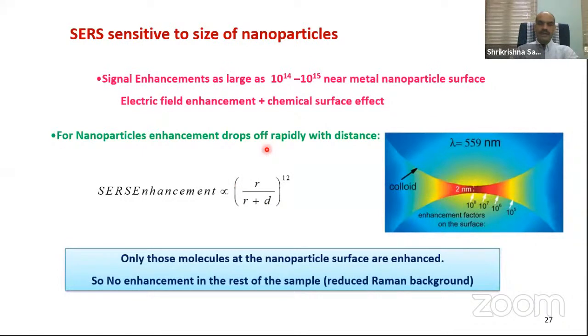It can be the pollutant, it can be an adulterant, or it can be a virus or whatever it is, and then I have to get the enhancement. Now the thing is that this enhancement is very critical, depends upon the size of the metal nanoparticle. For example, I am having these metal nanoparticles. These colors tell you the electric field around that particular metal nanoparticle after incidence of the laser. So when this laser is incident on those metal nanoparticles, what is happening? There is an enhancement in the electric field. And these numbers tell you the enhancement of the electric field.